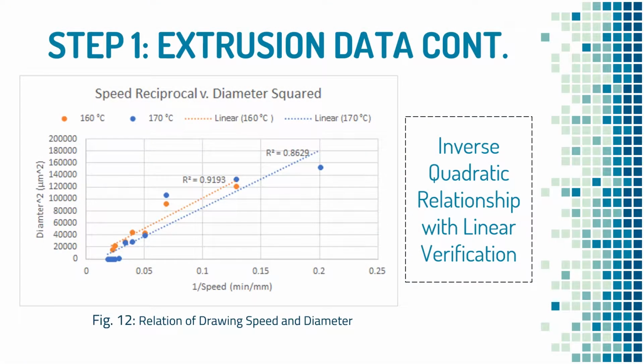So another important result of our extrusion is that we were able to establish a relationship between the speed at which we drew the fibers from the rheometer and its resulting diameter. We found that this relationship was an inverse quadratic relationship. In figure 12, you can see a linearized graph of the relationship between speed and diameter. Essentially what you need to get out of this graph is that the r-squared values, the closer they are to 1, the more accurate this relationship is. Okay? So it's important to understand this relationship because in the future, when we need to create a fiber with a certain diameter, we know the speed to get what we want.